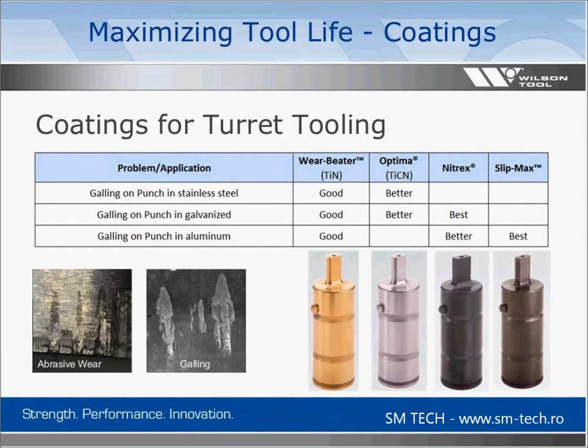A TiN coating, the gold coating, is a good all-around coating. Optima coating is an upgraded coating. It's great in stainless. It has a very low coefficient of friction and it adds significant hardness to the tool itself. Very good for stainless, however, it's not recommended in aluminum. Nitrex and SlipMax I see most often used in forming applications on those forming inserts to help reduce that stripping pressure coming out of abrasive materials.